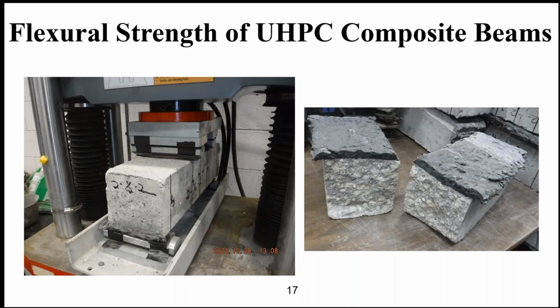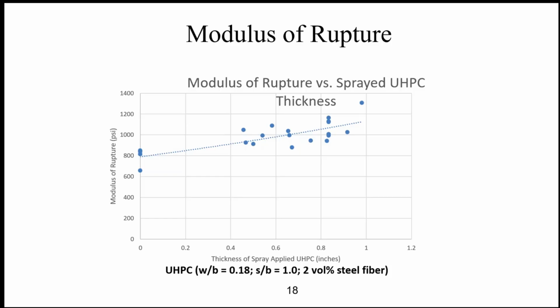These are small beams that are sprayed with the UHPC, and then tested under 4-point loading. Actually, these are some of the specimens that were prepared. The surface was prepared with exposed aggregate, it was moist, and then it was sprayed. So no reinforcement, nothing else. And you can see that the tensile capacity in the bottom of that beam, or the modulus of rupture basically, increases with increasing thickness. So for durability applications, I'll show you one means by which maybe you can decide what thickness you should apply.